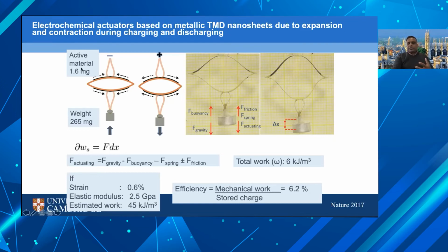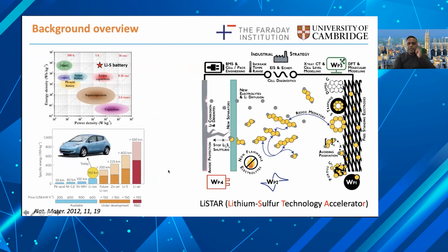And when one looks at the weight of the active material, around 1.6 milligrams, and the weight of the work that's being done, that's 265 milligrams, one can see that these electrochemical actuators are quite strong, in the sense that you're able to lift a weight that is 165 times more than the weight of the active material. So in addition to batteries and supercapacitors, one can also design these actuators.